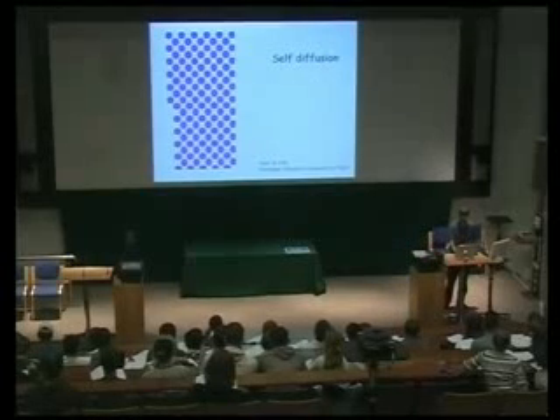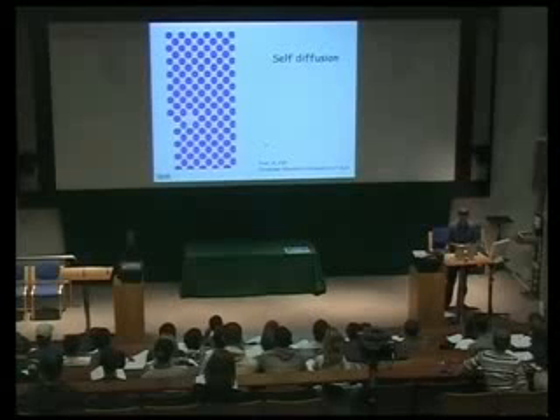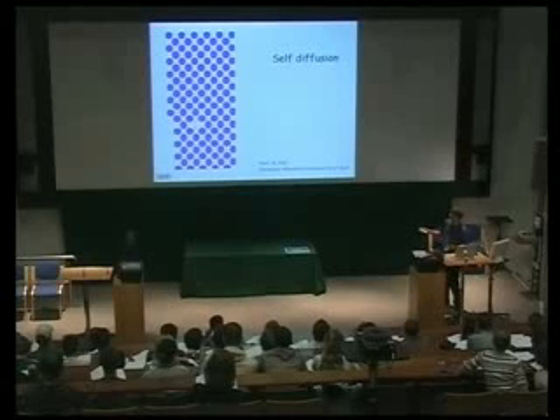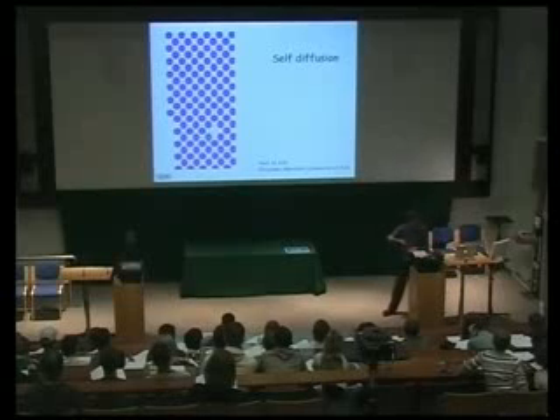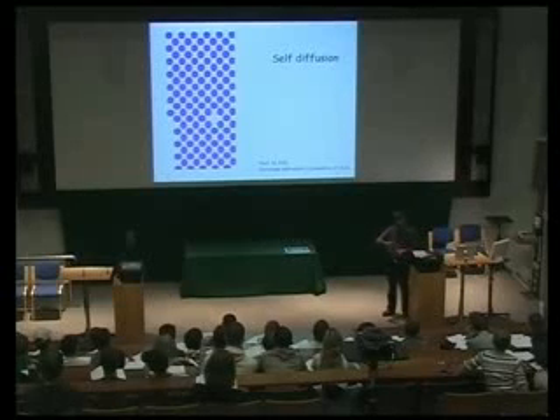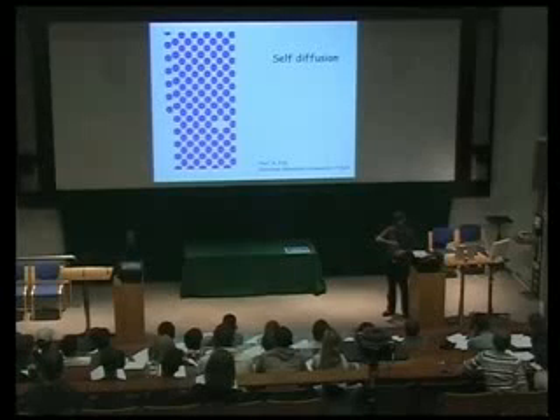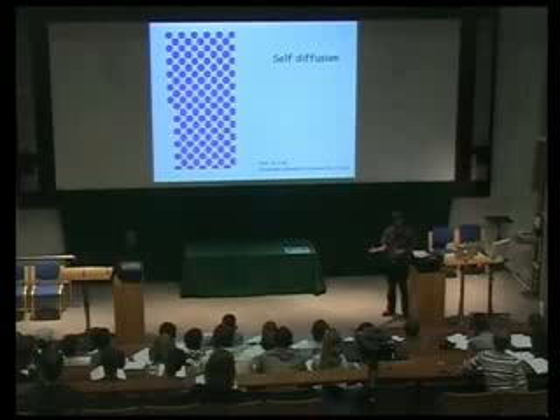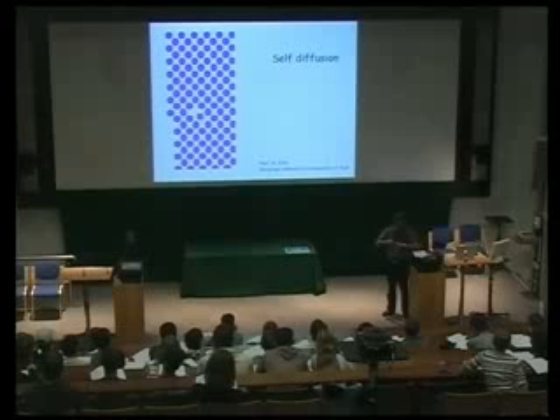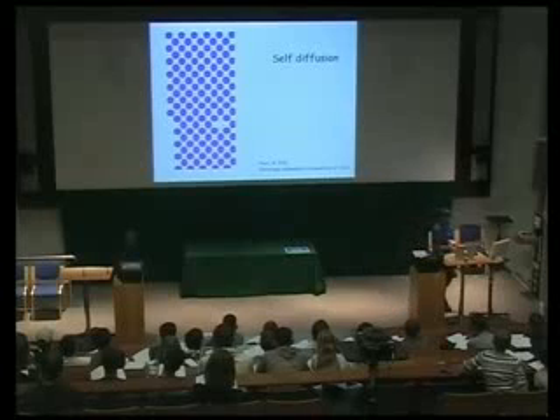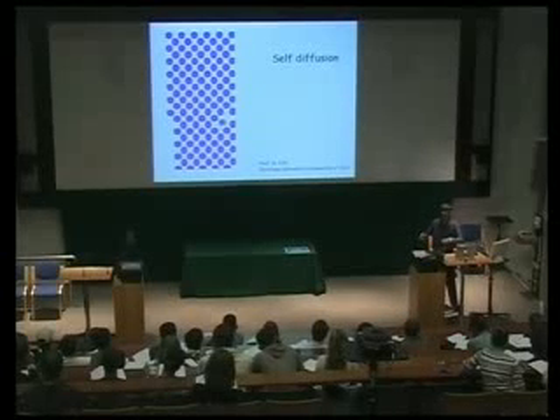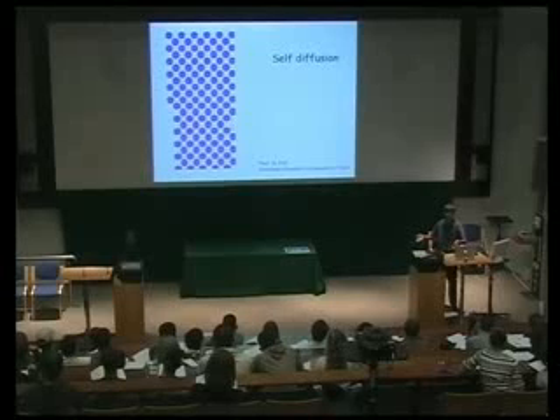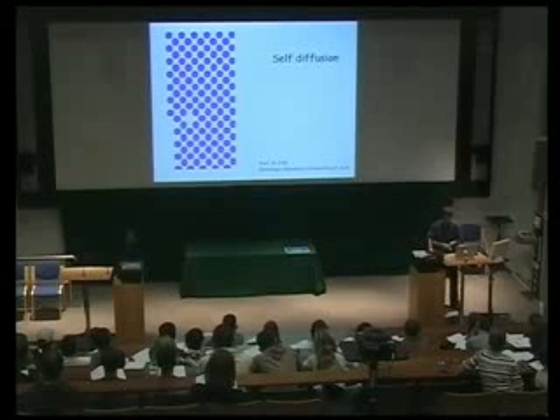Okay, so this is an animation of self-diffusion. You can see that it involves the migration of vacancies. In these movies, when you see an atom moving, it looks as if it's effortless, but there is an activation barrier in going from one position to the other, because as the atom moves, it's got to push some of its neighbors out of their normal equilibrium positions. So that's self-diffusion. Self-diffusion means that it's happening in a pure substance. So supposing this is copper, then the copper atoms are simply diffusing within a copper lattice.